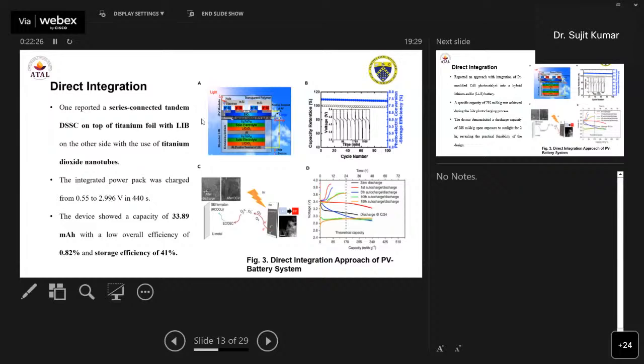You can see that in only 440 seconds they have charged and got around 2.9, or almost 3 volts, in the particular 440 seconds. Okay, so this device, when they have the tandem, continuous cascaded one, showed a capacity of 33 milliampere hours with a low overall efficiency of 0.82 percent and a strong storage efficiency of 41 percent.